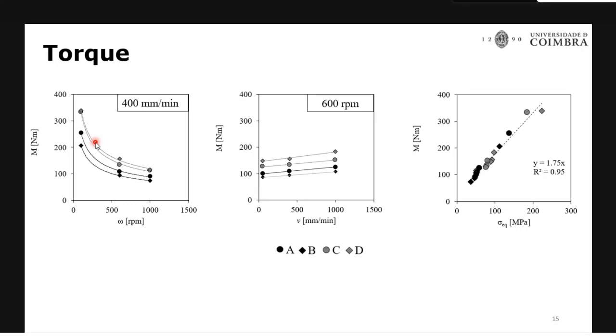Coming to torque, it is a very important indicator. It is the material response to the tool action. Here you can see that while increasing the tool rotational speed, the torque reduces, which means that with a higher rotational speed you will have higher temperature. That's why the material softening will be bigger, so the flow resistance will be lesser and the torque will be lower. The tool travel speed has a lower influence on the torque, but when it increases, the torque will be more, because the tool will not be there to make a complete stirring, and it is too fast, so the preheat zone will be very small and the preheat zone temperature will be very low also. So you will have a higher torque in this case.